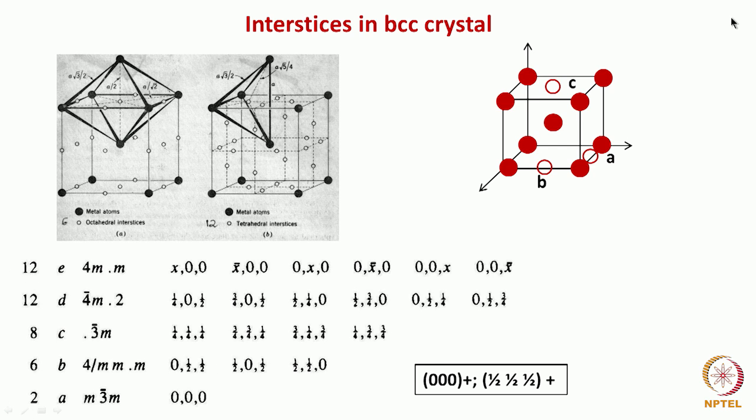In a BCC material, we are adding some impurities. Okay, this could be carbon, nitrogen or oxygen atoms which have got very small size. They go to interstitial positions. Okay. Then we can make out that three distinct positions are there depending upon the distortion which it will introduce, correct? That is one A position, B position and C position, because if an interstitial comes here, the strain is going to be more in this direction compared to the directions which are perpendicular to this.